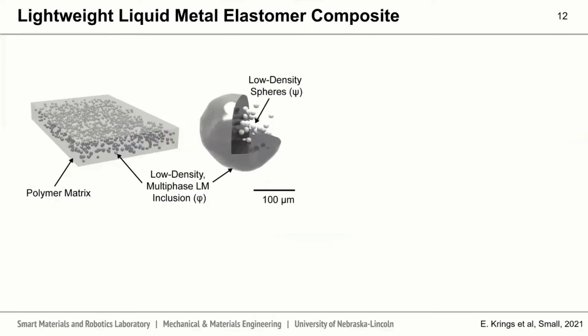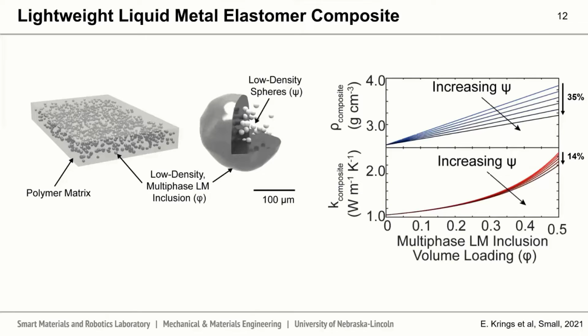So to do this, what we've done is we've introduced a secondary phase into this composite. Now we're introducing a low density phase into our liquid metal filler. This mixture is then loaded into the elastomer as before. From the theoretical prediction, the top graph shows the density of the composite, the bottom shows the thermal conductivity of composite, as a function of this multi-phase loading within the elastomer.